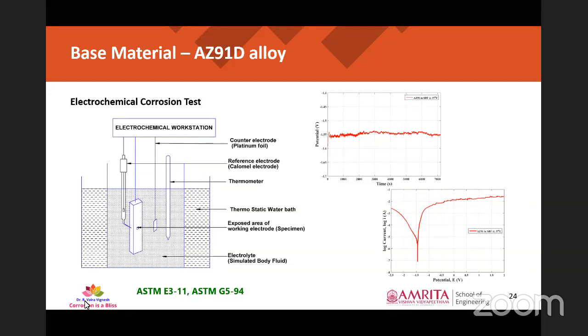Then the temperature was maintained at around 37 plus or minus 0.1 degrees Celsius. We have used platinum foil as our counter electrode and standard calomel electrode as our reference electrode. Then we have done potentiodynamic polarization test, and from that we have obtained corrosion potential and corrosion rate of these specimens.